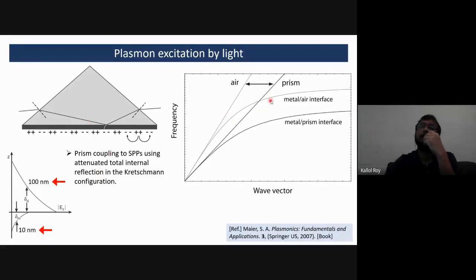For example, if we want to excite plasmons occurring at this metal dielectric interface, then we have to shine a light at a certain angle, which will connect via this metal thickness and excite this plasmon. This is a momentum matching phenomenon, and it depends on the thickness of the metal, because of the part of the electric field we are utilizing. If it is too thick, then we will not be able to excite the plasmons.